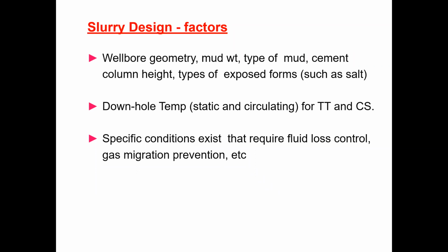Mud weight is also very important because density hierarchy has to be maintained. The cement slurry weight should be the highest. If you are using a spacer, all the properties of the spacer should be more than those of the mud, and all the properties like frictional hierarchy and density hierarchy. The density as well as yield point, gels and PV of the cement should be more than those of the spacer. So that hierarchy has to be maintained.